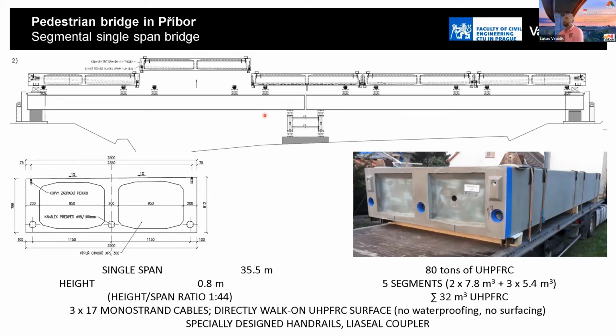Because this structure is made by UHPC precast elements, it was necessary to satisfy the condition of stresses in the joints. So normal stresses in the joints should satisfy the condition that for each possible loading combination, we have minimum 1 megapascal in compression in this joint. So that's why we produce the prestressing by 3 tendons. The tendons are realized by 17 monostrand cables. They are going through the walls, as you can see in these pictures.